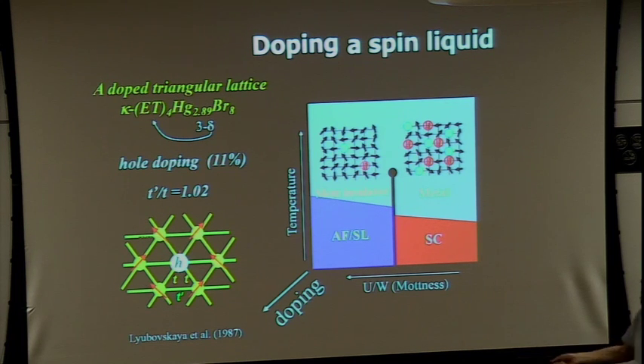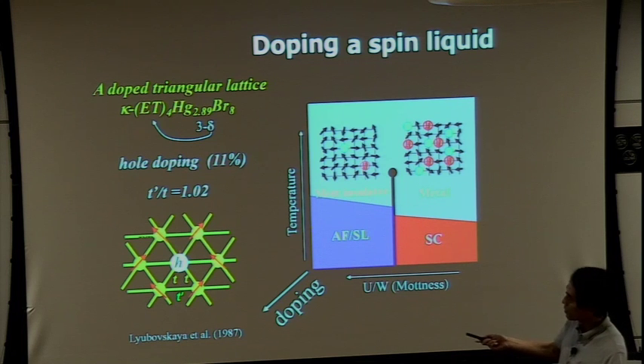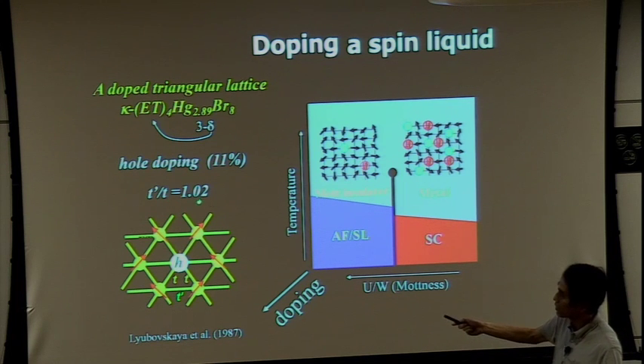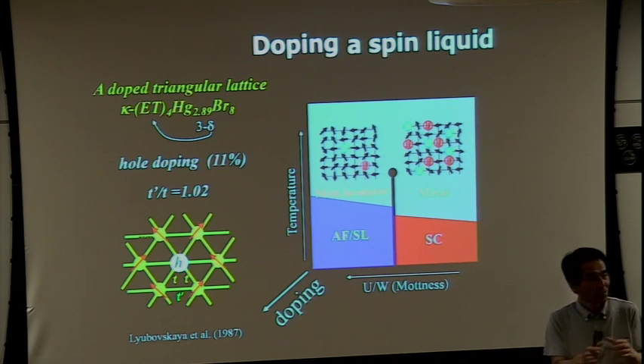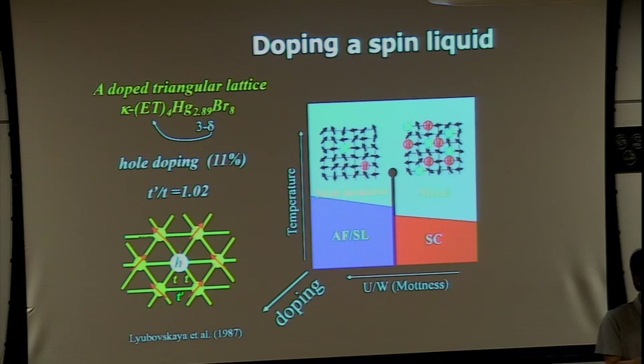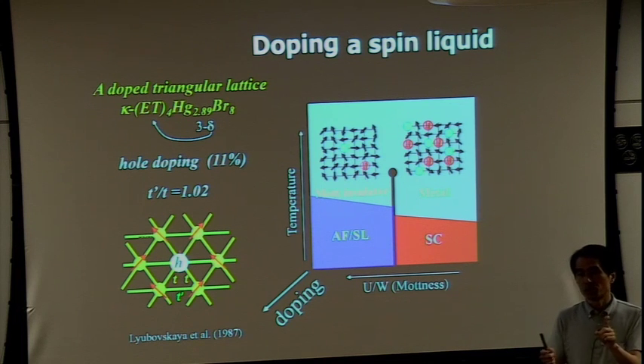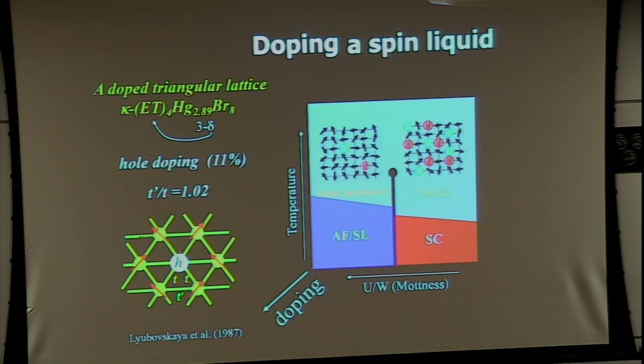An additional interesting point of this material is that t prime over t is unity. So we have nearly triangular lattices. So we have two nearly triangular materials. One is confirmed to be a spin liquid. And the other one is a doped material. This is the metal. So let's compare the magnetism and the conductivity of the two materials.